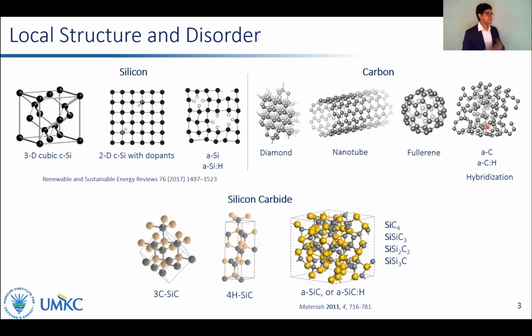The complexity further increases if you combine these two elements. For example, even crystalline silicon carbide exists in various forms, including cubic lattice and hexagonal lattice. Considering amorphous silicon carbide or amorphous hydrogenated silicon carbide, it lacks long-range order due to numerous characteristic configurations connected to each other randomly, making these materials far more disordered compared to single component systems such as amorphous silicon or amorphous carbon.